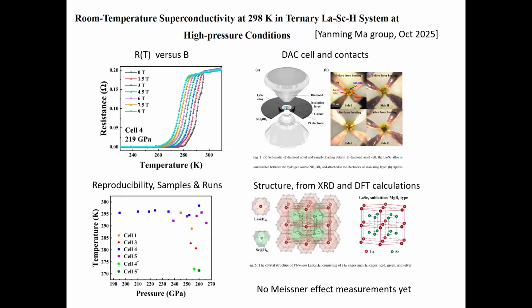Not cubic, it's hexagonal now, but a very simple crystal structure, which is easy to understand and easy to do the calculations for. And here is resistivity versus temperature. It's often found that at these very high pressures, the TC drop is not sharp. And it's because there's actually pressure-temperature cycling, with temperatures produced up to almost 2000 centigrade. So there's a lot of chemistry that goes on in preparing whatever happens.